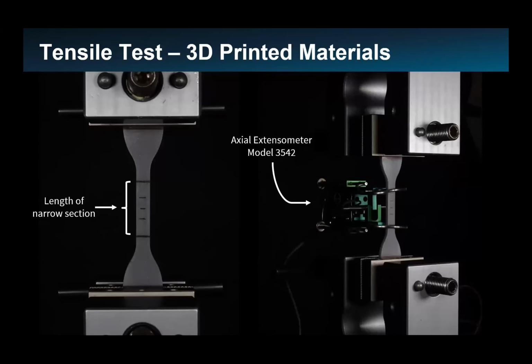Once we have the specimens, what we need to do is perform several tensile tests, as you can see in the figures. In the figure on the left, you can see some marks that are called the length of narrow section, where the specimen is allowed to fail. In the figure on the right, you can see the setup of the specimen and the appropriate extensometer for this type